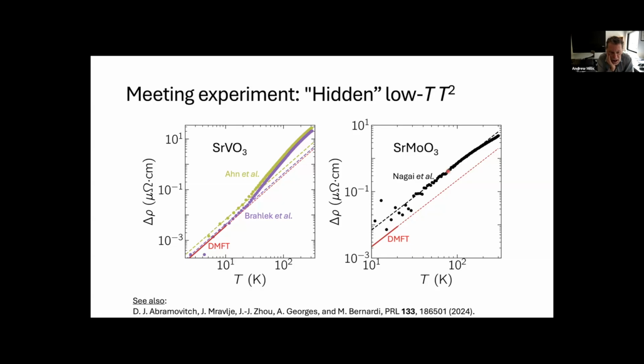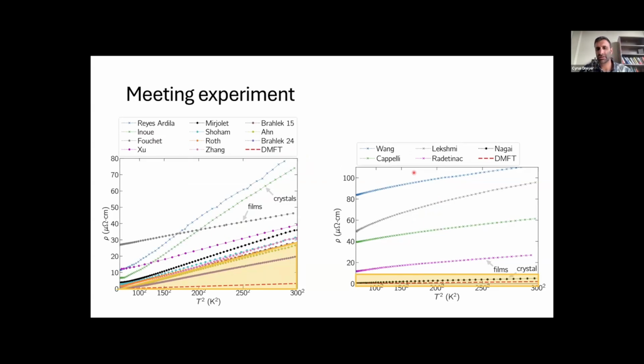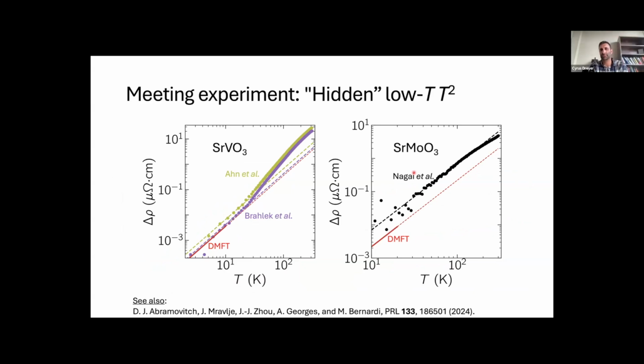A very brief question: in both of these cases, what's the value of the residual resistivity? Are we looking here at delta rhos which are bigger than the zero temperature value? No, I mean the residual resistivity. I don't have the actual values, but they're very low, tenths of a microohm-centimeter in the lowest samples. So we're talking about ranges where it's bigger than the residual. Because once you get into umklapp scattering, there's a big difference as to whether you have impurities around to break momentum conservation.